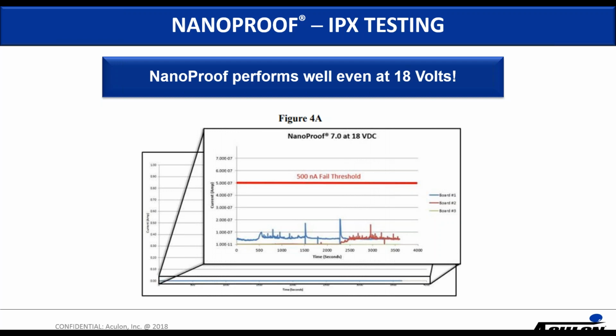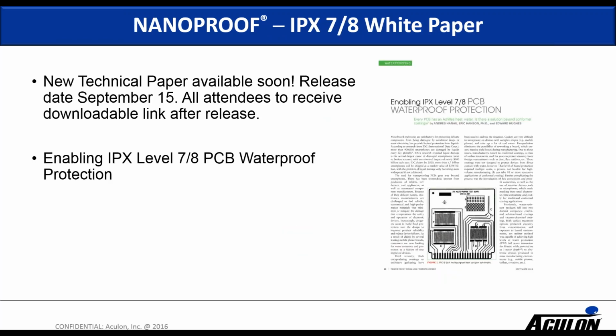And you can see there's some spikes up to maybe around 200 nanoamps on one of the boards, and the rest kind of stay flat around just under 100 nanoamps of current leakage. And a 500 nanoamp spike is considered the fail threshold. So all of these performed incredibly well. There was no observed corrosion on these boards after exposure to salt water at 18 volts.